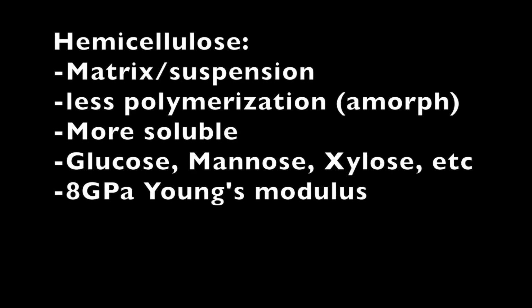Second largest component by percentage is hemicellulose, and that's the matrix or suspension that those cellulose fibers are held in. It's a lot less polymerized, as in amorphous. It's more soluble in water, and instead of just being glucose, it's also made of mannose, xylose, etc., a couple different types of sugars, and has a much, much lower Young's modulus of around 8 GPa. So if you're thinking of this in terms of like a fiber composite, like carbon fiber, think of cellulose as the aramid or glass fiber strands, and then hemicellulose as the epoxy resin binder or matrix.